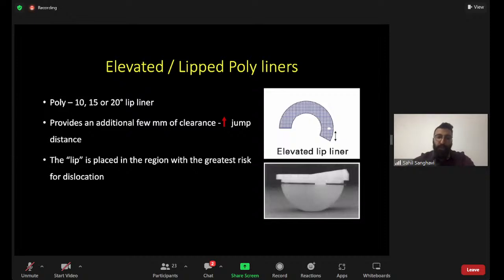So if you're doing a posterior approach, you would ideally place this in the posterior-superior segment of the acetabular shell to prevent posterior dislocation. However, one point you should be careful of here is that if you have increased version in your cup, it's better to go in for a neutral liner than go in for an elevated liner, because while this elevated lipped liner will give you some protection against dislocation, it may also cause impingement in a figure of 4 or FABER position.